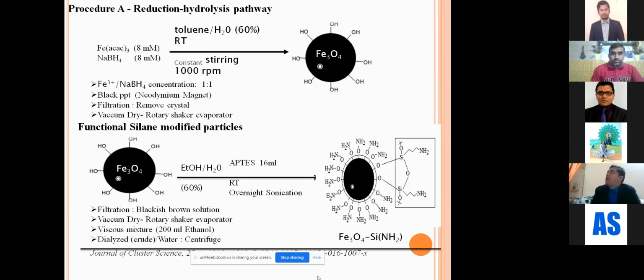And after getting this iron oxide nanoparticle, we have functionalized them. I told you that quaternary ammonium compounds are very effective in controlling the biofilm formation, and that is why we have modified the surface with the help of aminopropyl triethoxysilane and with sonication also. And in the presence of ethanol, we have functionalized the surface with the amine, because I told you there are three ways of controlling or releasing the nanomaterial at the bio-nanosystem scale.